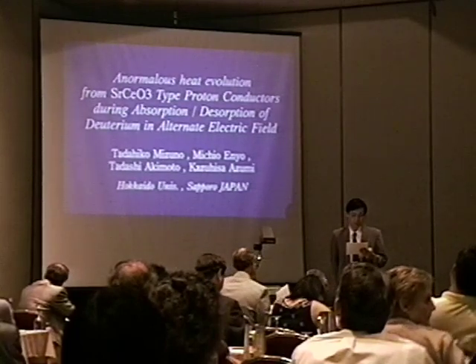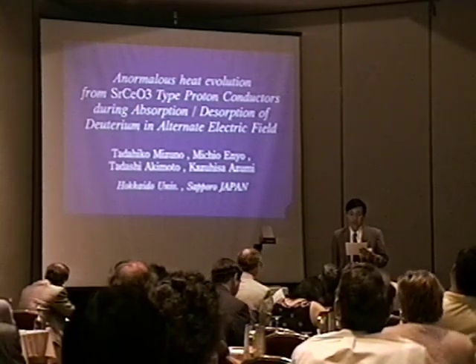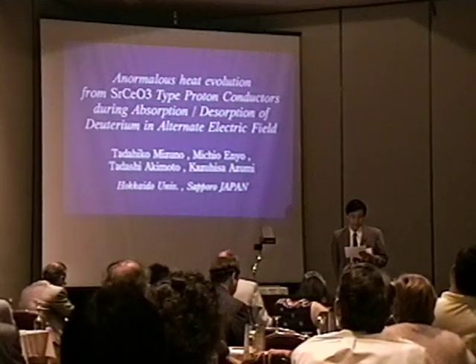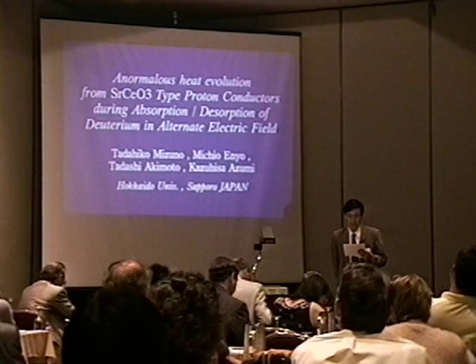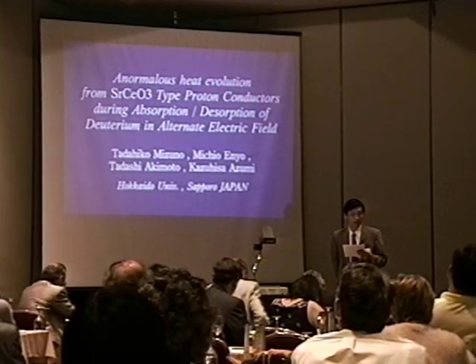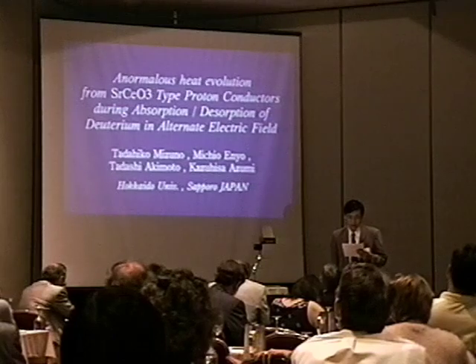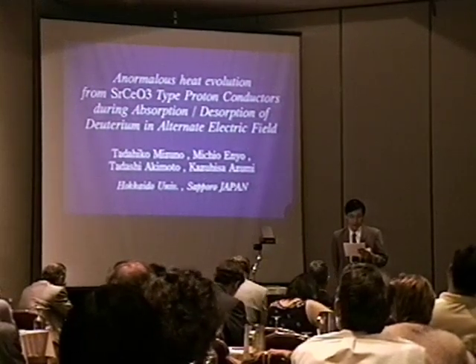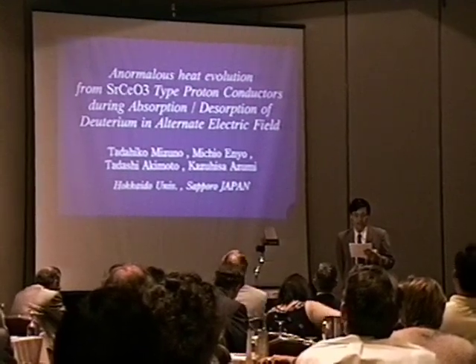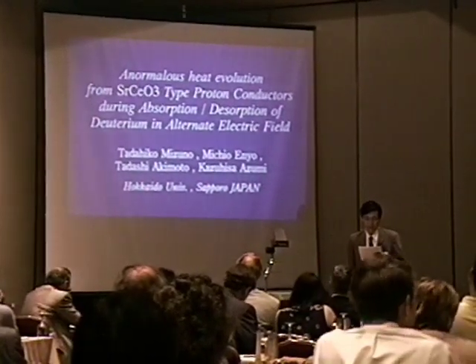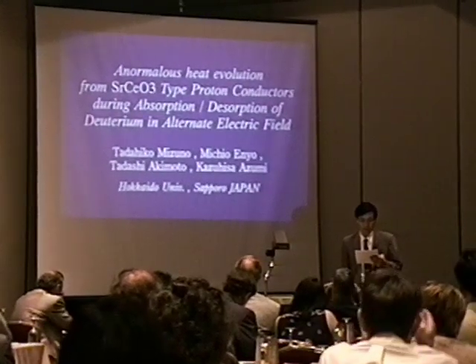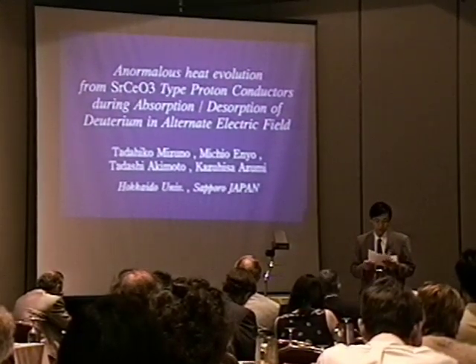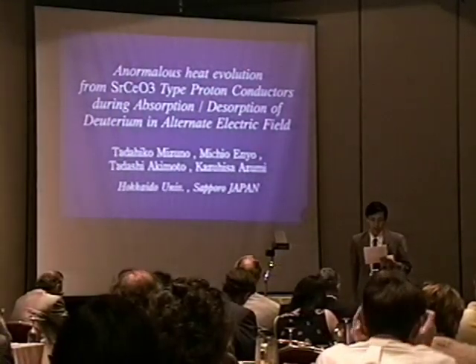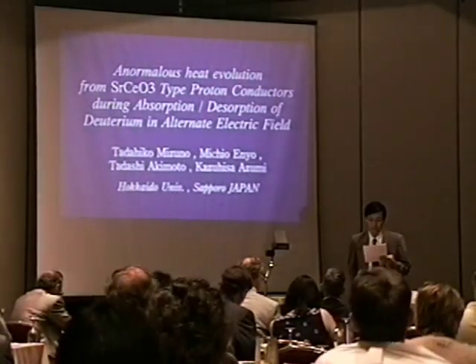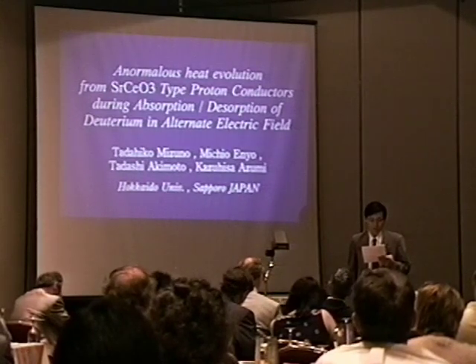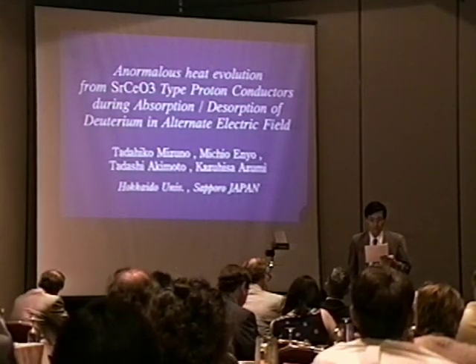A common system is electrolysis of heavy water with a palladium electrode. An experimental difficulty there is that usually charging deuterium into the sample needs an extremely long time. Takahashi observed heat generation during cyclic changes of current in heavy water electrolysis. This suggests that a kind of perturbation in electric current may be advantageous. Similarly, Yamaguchi reported helium production from a palladium plate. Its surfaces were covered with manganese oxide and gold plating.